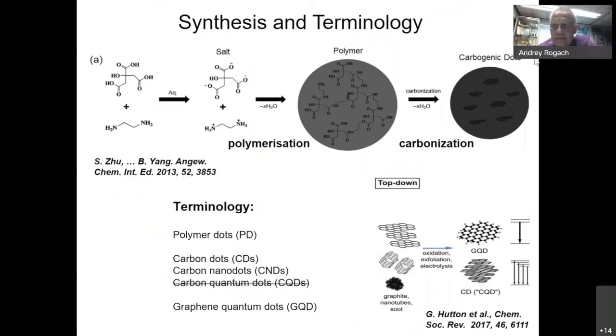So here I place some pictures to talk a little bit more on how the synthesis occurs. So here we again take the precursors, pretty much what I told you before. We put them in water, these precursors can become charged, right? And then we apply temperature, normally in an autoclave, or we apply microwave treatment. And then these two precursors will start to react with each other. And the first step here, we call it polymerization. So Igor should be very familiar with this kind of terminology and what will be formed here. And actually what is formed at this stage, when temperature is not very high, some people stop here and they claim to make polymer dots. So this is already a nanoparticle. You can isolate them and you can treat them as nanoparticles. You can redisperse them in solvents and so on. And they consist of polymers of this particular composition if we choose these particular precursors, right?